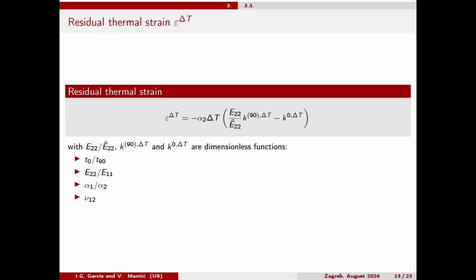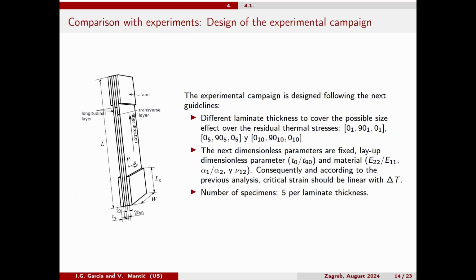So what we expect is that the residual thermal strain, this term that adds to the mechanical strain, taking into account the residual thermal stresses, is linear with the temperature. And this is what we want to evaluate experimentally.